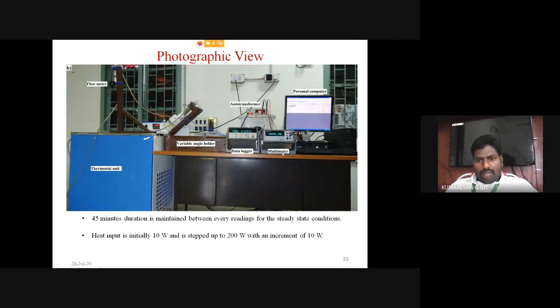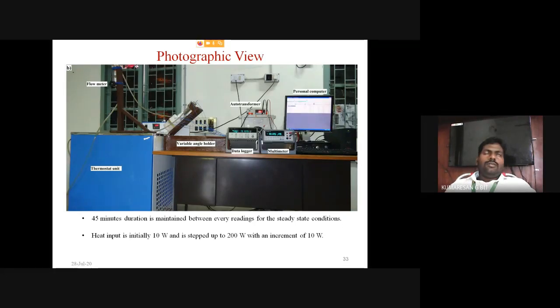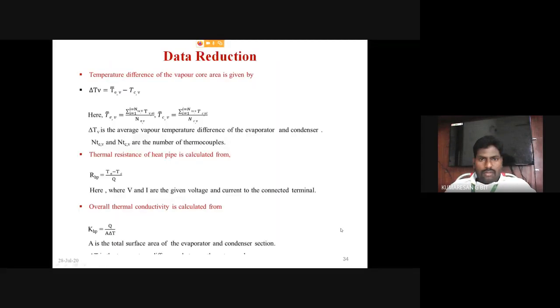Then a data logger, multimeter, and the personal computers. These devices I have already explained to you. Okay. Then finally, a 45 minute duration is maintained between each and every reading to attain the steady state condition of the particular operation. The heat input is initially 10 watt and is stepped up to 200 watt when I have used the composite wick structure in the heat pipe, with an increment of every 10 watt.